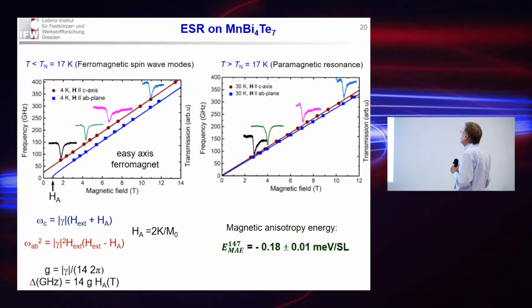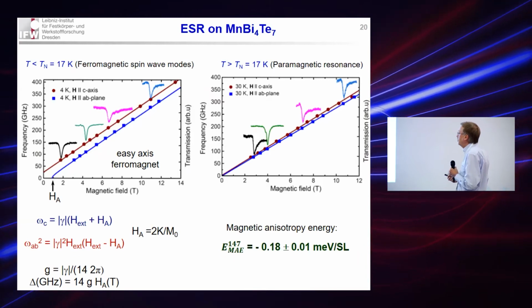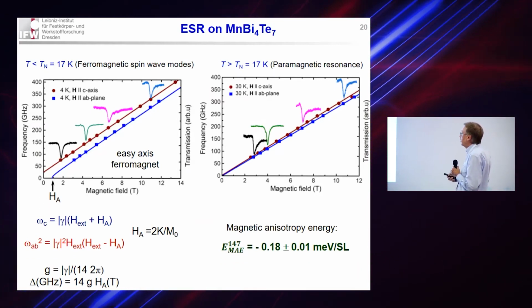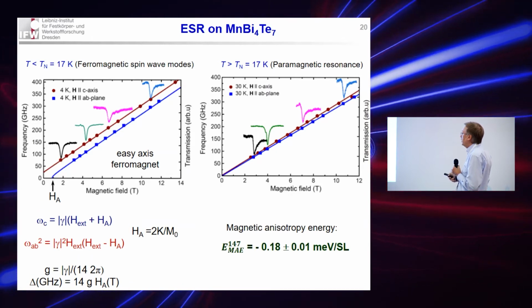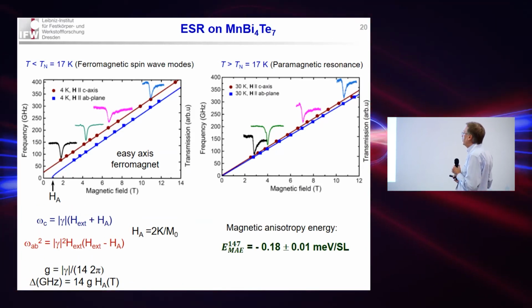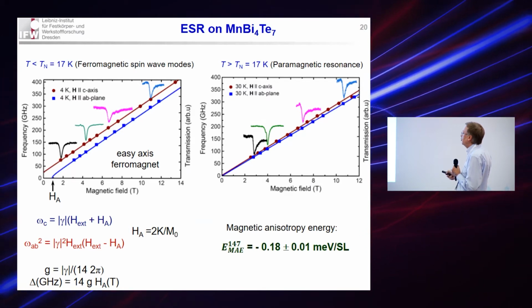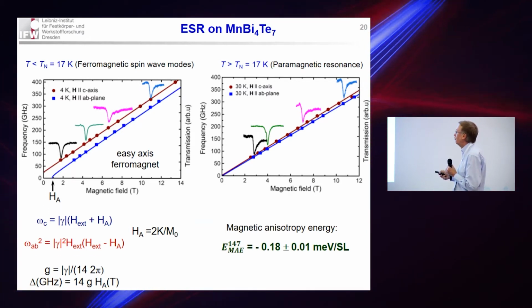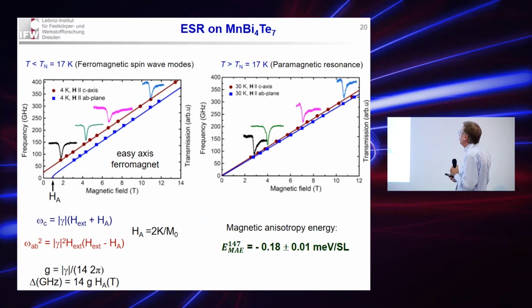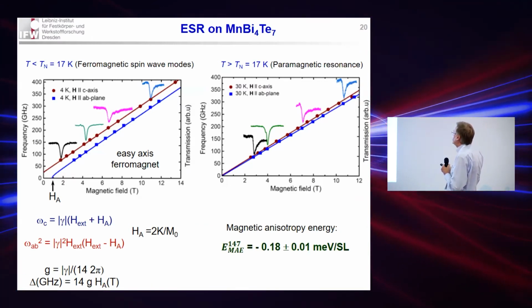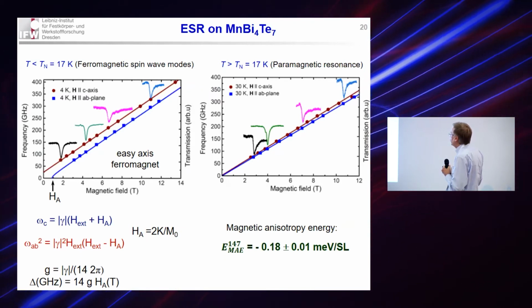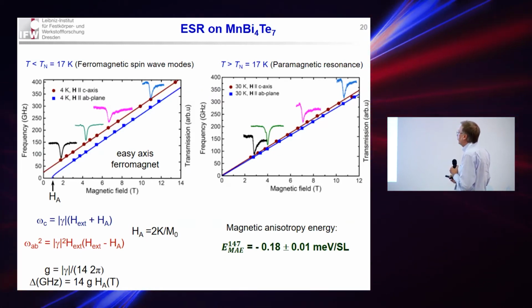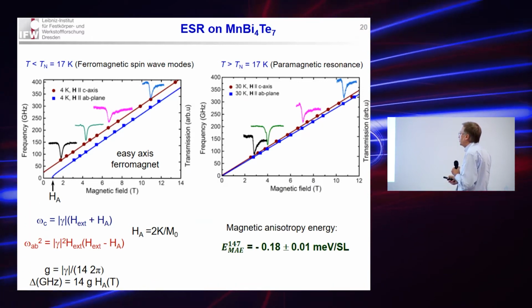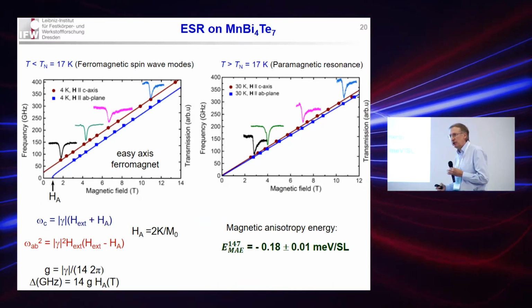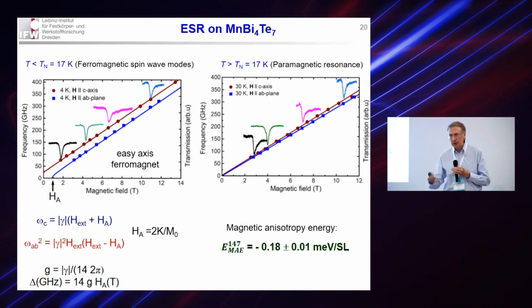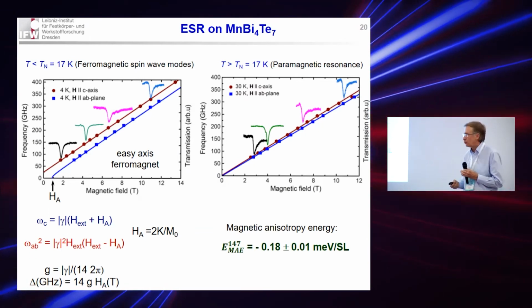First we started with 147, which showed a very simple excitation spectrum. In the magnetically ordered state, it's just a single line which has a linear dispersion in the magnetic field, at a frequency of about 250 gigahertz, approximately 1 millielectron volt. One sees this linear dispersion; when one turns the field in plane, this resonant branch simply shifts to lower energy. And if one extrapolates this branch to zero field, one sees a finite frequency offset, meaning a finite energy is required to excite a spin wave. This is the so-called magnetic anisotropy gap.